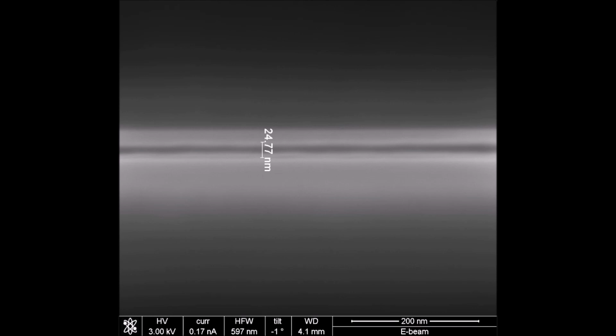So what is the thickness of the near surface region of the specimen? Again, it's not necessarily straightforward to do that, but again, if we want to get a rough idea, we again use that dark line as the reference for the top of the lamella, and we can see as we move outward from that, we have two somewhat abrupt changes in contrast on either side of it, sort of where you have these bright lines that end, or again, you have abrupt transitions. So making a measurement here, we get about 25 nanometers. And that's one method that you can use to get a rough idea of your lamella thickness. If you wanted a more accurate measurement of the area you're analyzing in the TEM, you would actually need to use techniques that are specific to the TEM, which obviously can only be performed while you're performing the TEM.